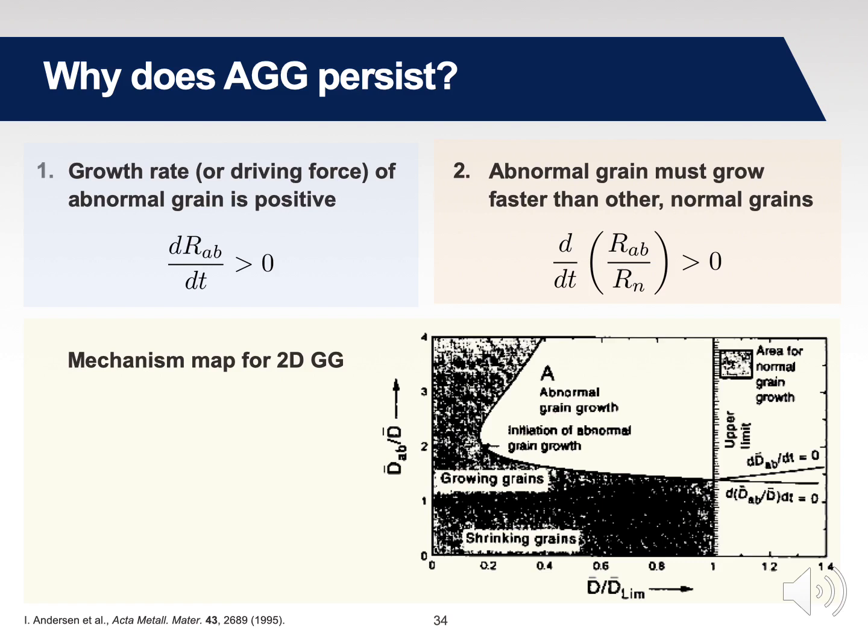And so when you plot these 2 curves, the inner locus of these 2 curves gives you the characteristic fields for which abnormal grain growth is favored and the conditions where it should persist. The y-axis here is the size of the abnormal grain with respect to the mean grain size, and the pinning strength of the particles, which is what the x-axis represents.